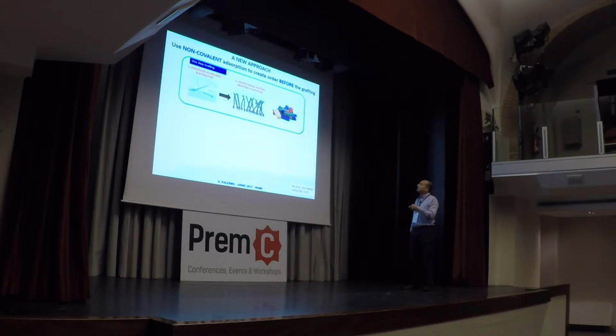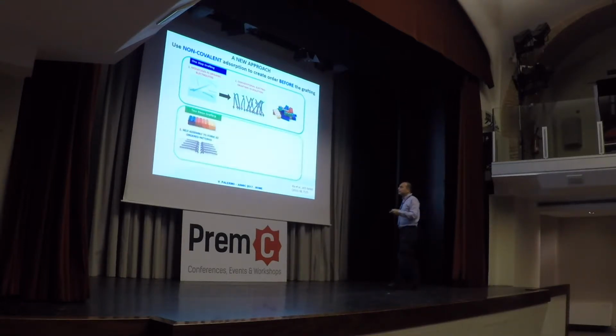This is the method I just described. So you have freely floating molecules in solution. You apply the pulse, they stick, but in a disordered way. What we did was to exploit the advantage of molecules to self-assemble on graphite and also on graphene. So first, this molecule physisorbs on graphene. That's why it's an equilibrium. They can reach a very ordered layer, forming two-dimensional crystals ordered on them.